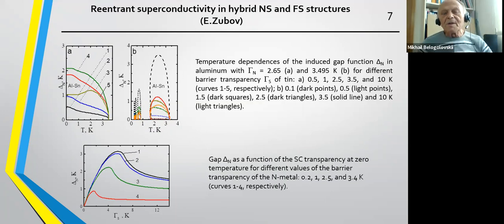So the first part, about the proximity effect, I start with re-entrant superconductivity. It is not the experimental figure, but something similar can be observed experimentally. So you are going from above, from higher temperatures, and suddenly at the critical temperature, the superconductivity appears. After that, it disappears, and at lower temperatures appears again and disappears. So there are 2 regions where the superconductivity exists. Usually, it was observed in samples with magnetic impurities and was related to magnetic ordering in the studied samples.